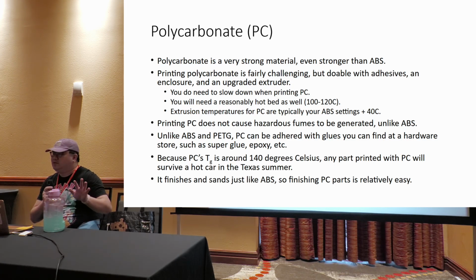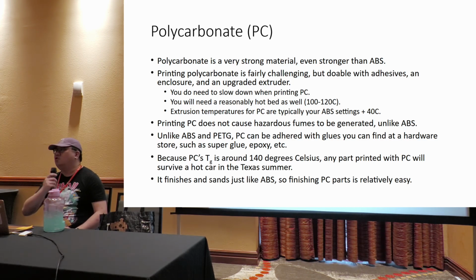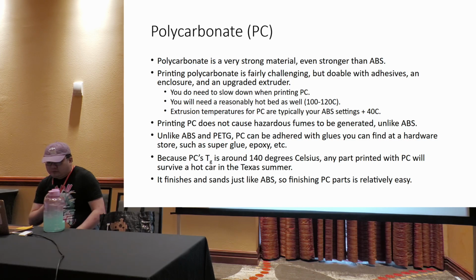I think PET has kind of fallen out of favor with some of the armor folks because they found out that you have to use very special adhesives to adhere to it. And if you run out, you'd be waiting several days for more adhesive. Polycarbonate can be adhered with super glue, epoxies, polyurethane glues, basically it works with a lot of different glues.